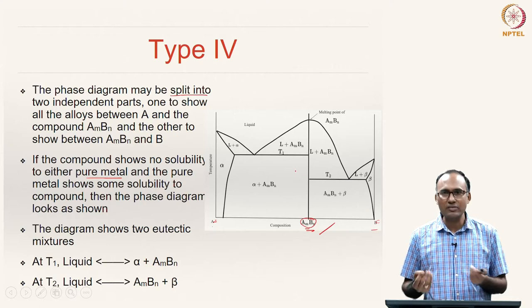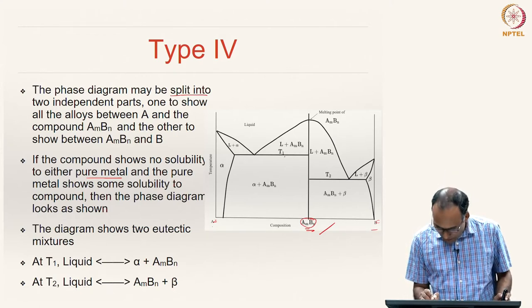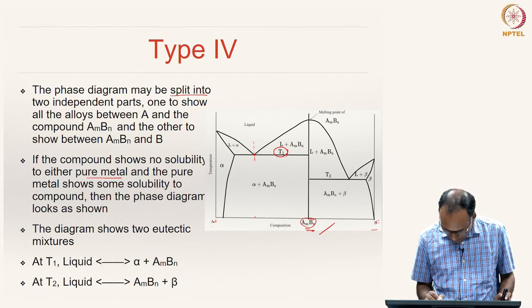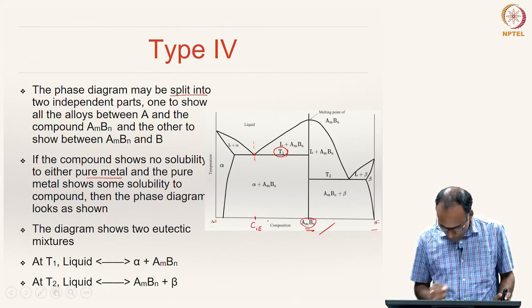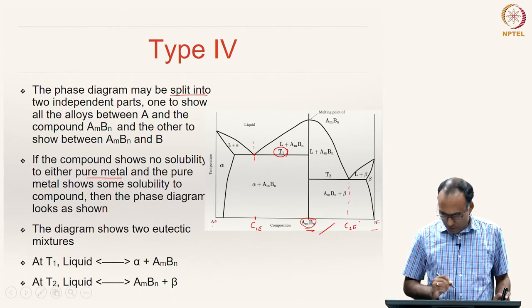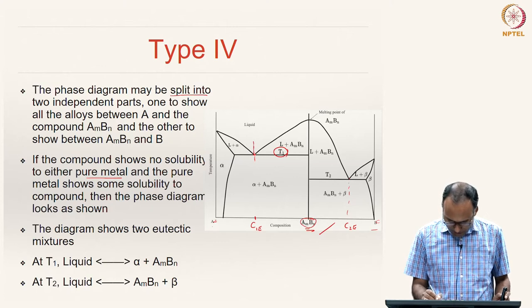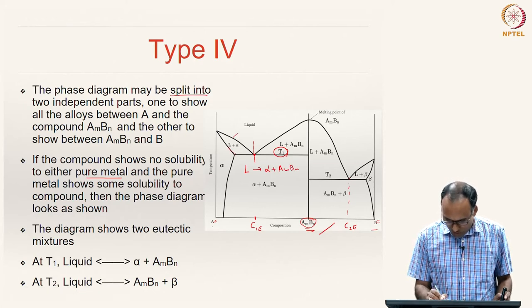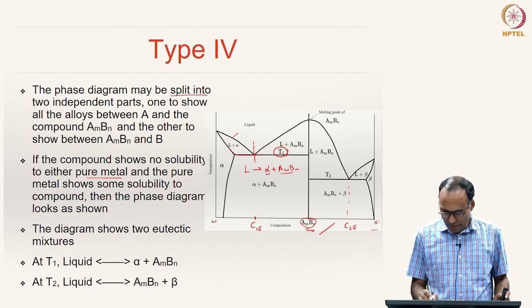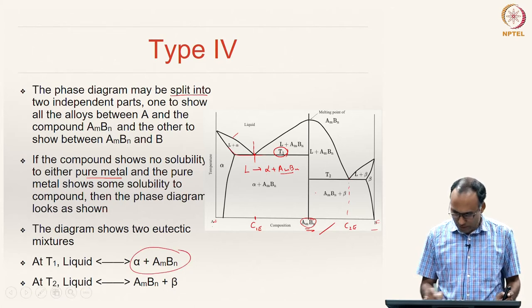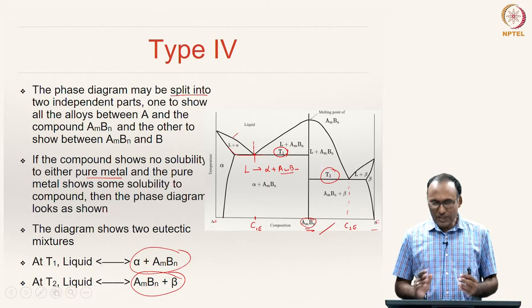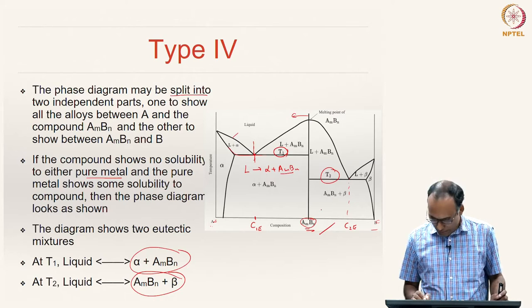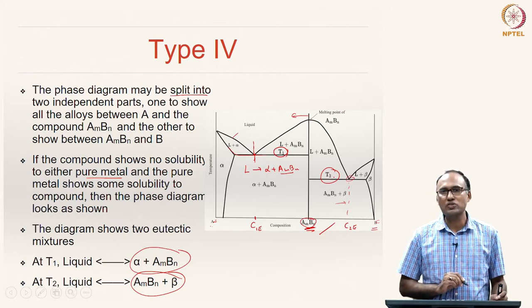However, if there is some solubility, the phase diagram may look slightly different. At temperature T₁, cooling an alloy of composition C₁E, the liquid is transforming to alpha plus A_M B_N—two solids—because this is the liquidus line and this is the solidus line. So this must be our eutectic reaction at temperature T₁. Similarly, at temperature T₂ there is another eutectic reaction. Looking only at the left-hand portion between A and A_M B_N, you have one eutectic temperature; looking at the right-hand portion between A_M B_N and B, you have another eutectic temperature.